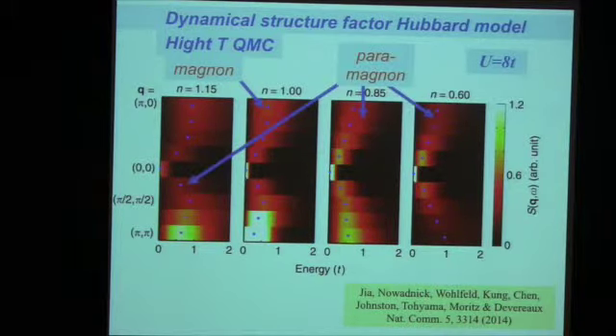So now let's look at the doped system. And at least what they see for the smaller cluster at high temperature is indeed there is something like a paramagnon. This is 15% hole doping, and the magnetic excitation when you go to pi 0 remains. When you go to pi half, the magnetic excitation actually becomes more pronounced. And even if you go to 40% doping, which is quite a lot, there in S of Q and omega, there is spectral weight there. It's kind of very bizarre. So the paramagnon in the pi direction is easy to understand. Pi 0 is not so easy. Okay, you know it. Yeah, it's true. It's my next slide.